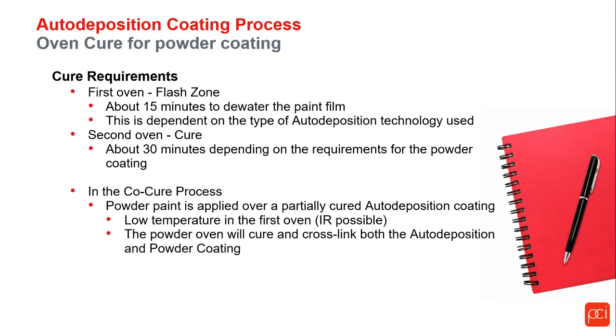If someone was to go on beyond the auto-deposition process and then use a top coat, the only difference here would be that we would change the way that the oven cure is done. To top coat, there would be two ovens utilized. In the first oven, it would really be used to dewater the auto-deposition film. In the second oven, it would be a full cure of the powder coating. We call this the co-cure process.